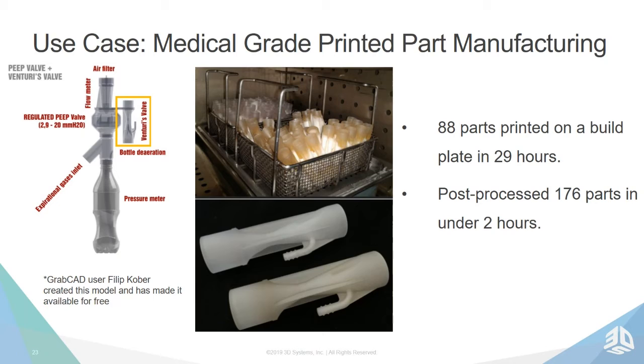So in this particular photo, 88 parts were printed on the MJP build tray in just 29 hours, and then 176 parts were post-processed in under 2 hours using our Easy Clean steam system, followed by a convection oven. So most of the time taken was in melting the bulk support material away, while most of the labor was just using soap and water to remove the final residue. Overall, the process amounted to about 30 seconds, or maybe just a little bit more than 30 seconds per part in terms of post-processing. And that's, again, 176 parts post-processed in under just 2 hours.